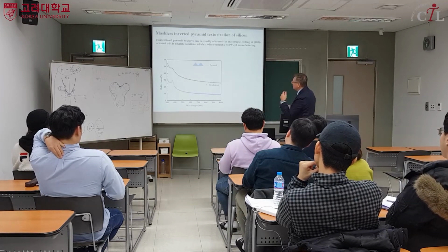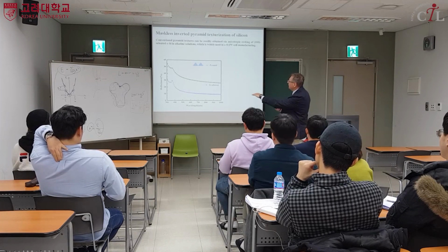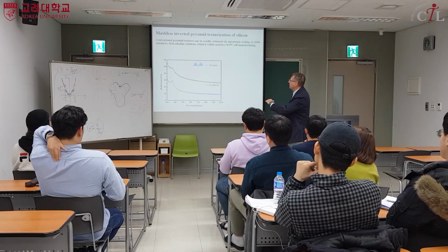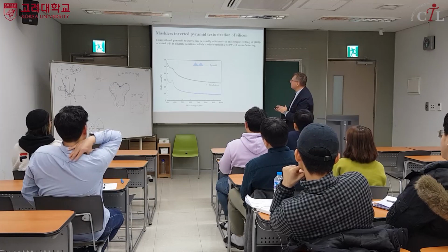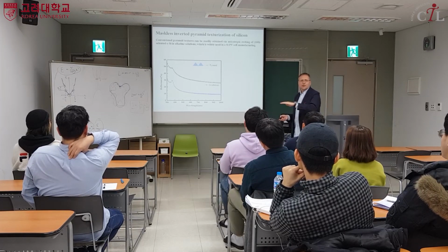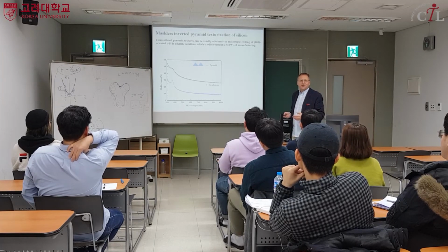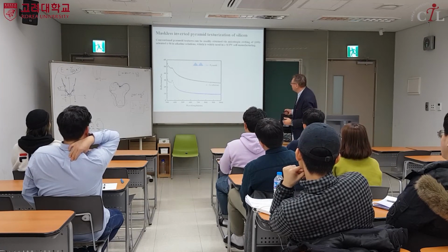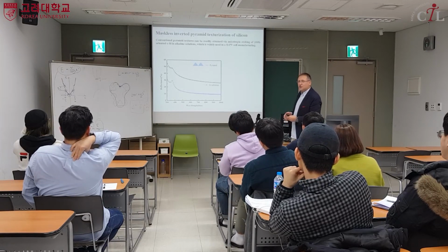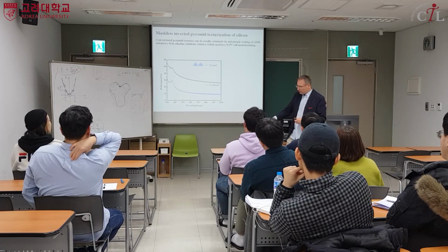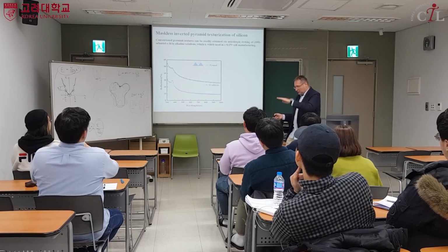So for instance, this is a very mirror-like silicon wafer. It almost reflects 50% of the light. You never make a good solar cell of a normal silicon wafer, because then you lose 50% of everything. So what you have to do is texture. The normal texture is pyramid-like texture, very easy to do. You put it in a solution, and instead of a mirror-like, very nice surface, you get so-called pyramids.